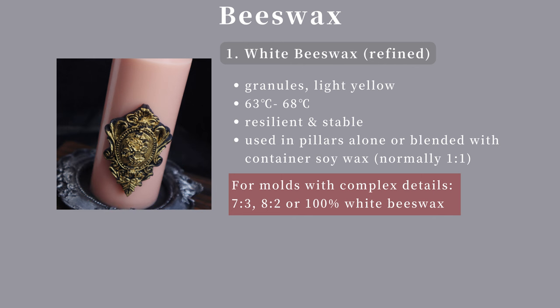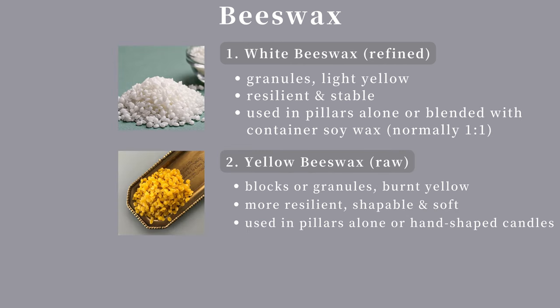Please note that the pouring temperature should be above 90°C for 100% white beeswax candles, and heat the molds with a heat gun before pouring. If you prefer to skip the heating process, the pouring temperature should be above 100°C. Yellow beeswax is softer and more resilient than white beeswax. Since it's naturally yellow, white pigment is required to color the wax so we can adjust the color from this yellowish base.